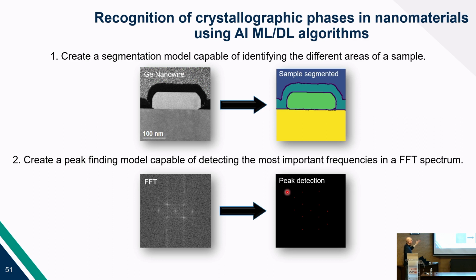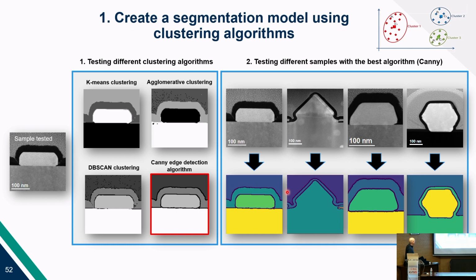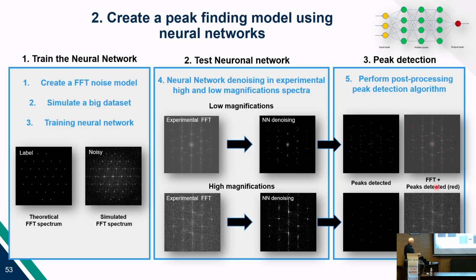This is the way to analyze your data by automating using convolutional neural networks or machine learning, depending on the different parts. And we are trying different types of clustering algorithms in order to do segmentation and identify the different parts of our materials. These are nanowires, and these are core shells in some cases with the substrate. And we are trying to identify this automatically and also trying to denoise the patterns, the fast Fourier transform patterns or the diffraction patterns, in order to identify every spot.